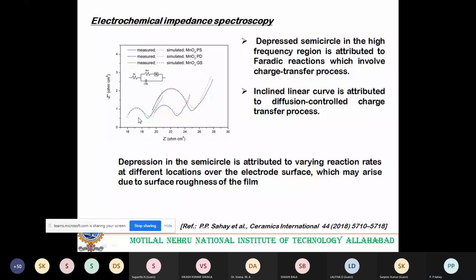Faradaic redox reaction means that it is a charge transfer process. So basically, the idea is that during the electrochemical process, two processes dominate, and these two processes occur simultaneously. One is the capacitive behavior of the charge separation at the electrode electrolyte interface, where there is also a charge accumulation at the interface, and another is the resistive behavior of the electron transfer. So these two processes occur simultaneously, leading to the semicircular response.